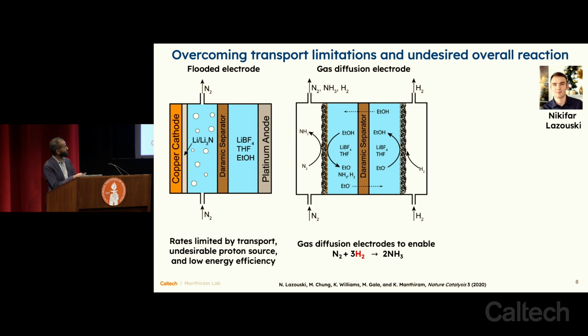So there are three different phases, solid, liquid, and gas, that could all be brought together within this porous medium that we call a gas diffusion electrode. And we reasoned that if this were implemented, then both gas and liquid could meet each other at the solid surface. So we would no longer have this journey of nitrogen gas from bubble to surface of the electrode be limiting, because the gas would have direct contact with the surface of the electrode as shown here.